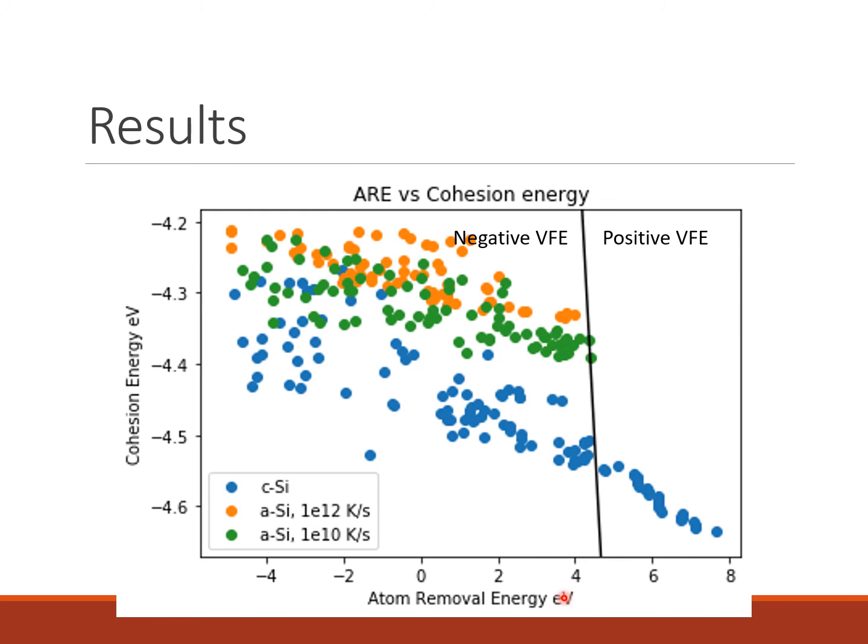If the atom goes to a crystalline silicon structure, then it is defined by the cohesion energy of diamond crystal silicon, or 4.67 electron volts, which would be a straight line. However, if it goes to a spot of amorphous silicon, then it is that particular cohesion energy, which would translate this line, and it would still be vertical.